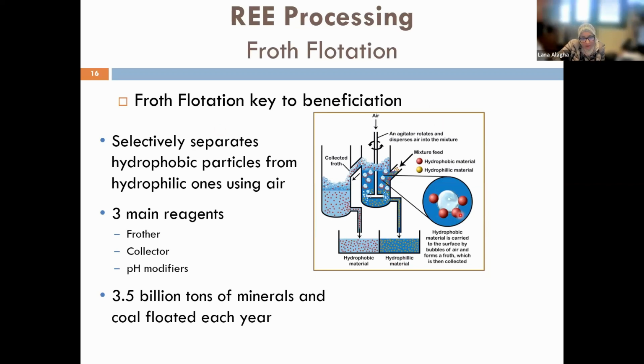And you can see here, this is the air bubble, and this is the hydrophobic material that is attached to the air bubble. And this shows the relative size of your mineral particle and the size of the bubble. In a conventional flotation cell, the size of the bubble is between 0.5 to 2 millimeter in diameter, which is about 2,000 micron or so.